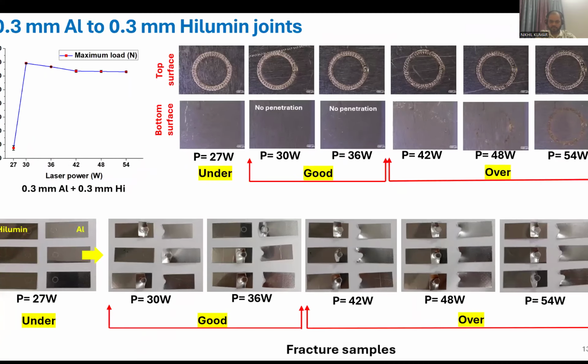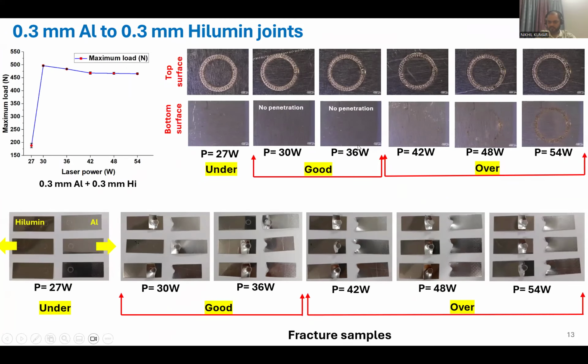So you have two parameters ready now, 30 and 36 watt. You can consider either one as a good weld, because in both cases you are not penetrating the bottom sheet, which is good for the battery cell, because it is filled with electrolytes. You are also fulfilling the criteria of welding: the material is failing, the weld is not failing at the interface. This one is considered an overweld because, as soon as you break the samples, it is over penetrated into the bottom sheet. This is definitely not applicable to our application, where you are going to weld the battery cell. The maximum strength you are getting is 500 Newton for the aluminum to aluminum can.